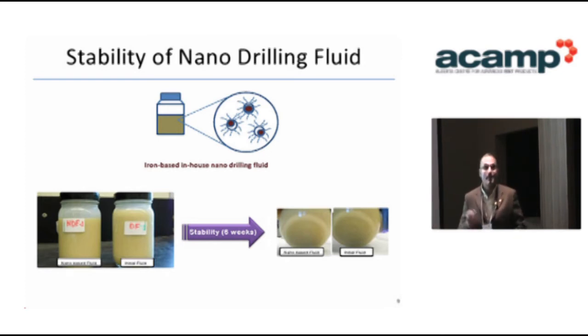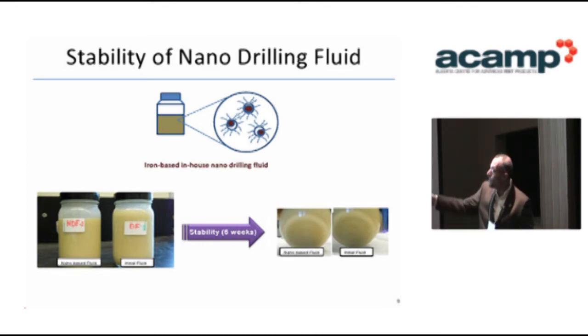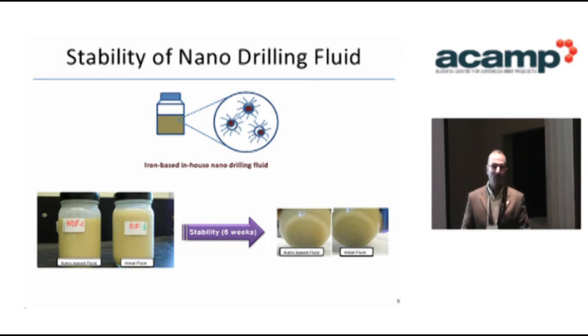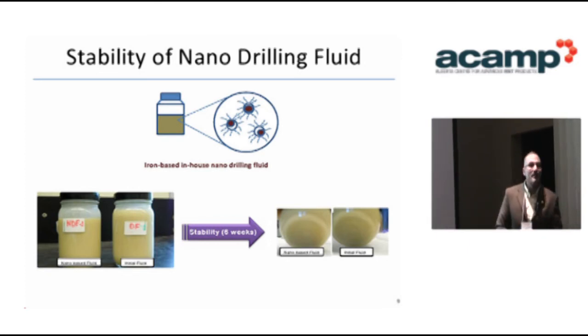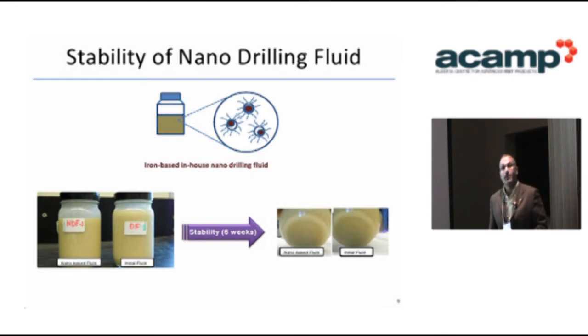The first thing we looked at was sagging. For those in the drilling fluids field, sagging is a big issue — you must ensure that upon formation of nanoparticles well-dispersed in the drilling fluid, the drilling fluid maintains its integrity and doesn't separate into solid and liquid phases. Unfortunately I can't discuss the details of how we formed our nanoparticles as it's part of a patent application. After forming them, we looked at stability, and indeed the drilling fluid was stable for over six weeks with no segregation and no separate solid or liquid phases.